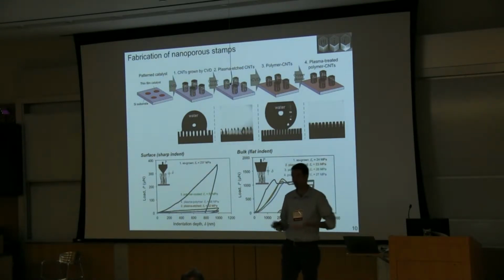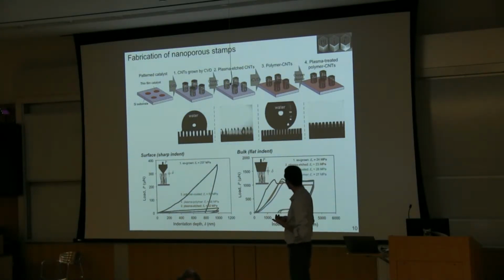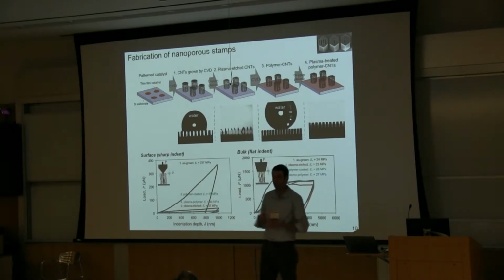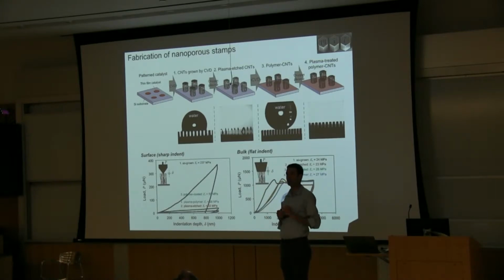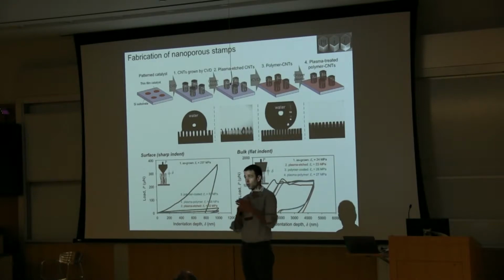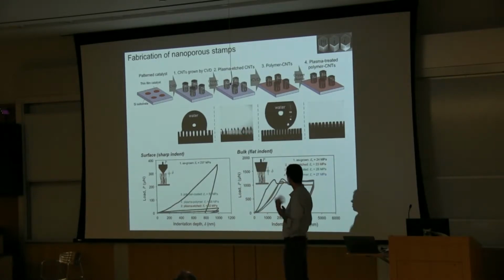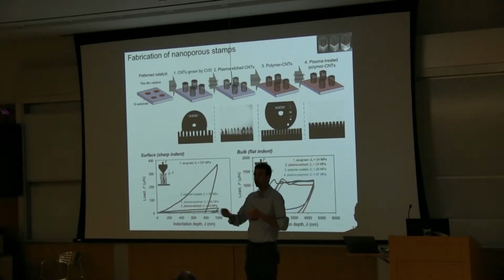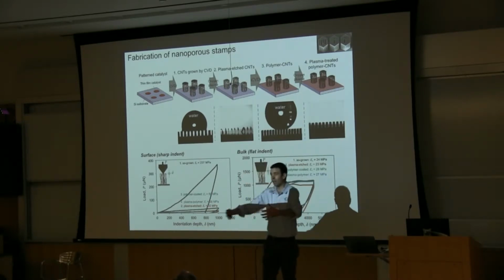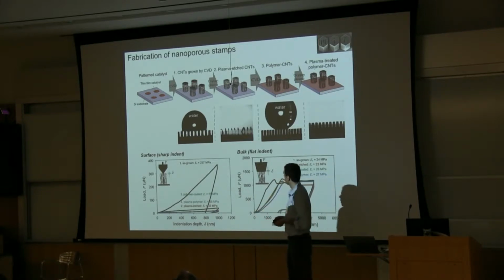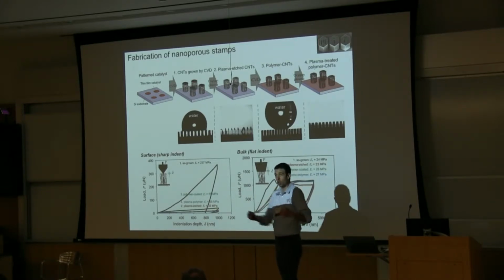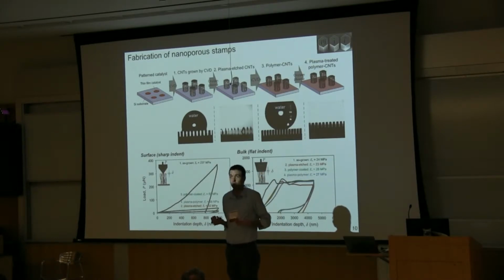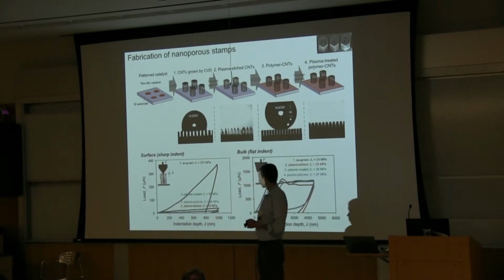So they don't work as we take them out of the oven, and we have to satisfy a few requirements. If you remember the schematic of the process in mechanical contact, we need good intimate nanoscale contact between the stamp and the substrate. So we need to make the stamp soft both on its surface and in the bulk. The other thing is we need to make the stamp wettable to the ink we choose, say a water-based colloidal ink, and third, we also need to make it resilient to elastocapillarity. There have been a lot of studies of carbon nanotubes where beautifully you shrink up the nanotube forest using capillary forces that exist when a liquid meniscus recedes.